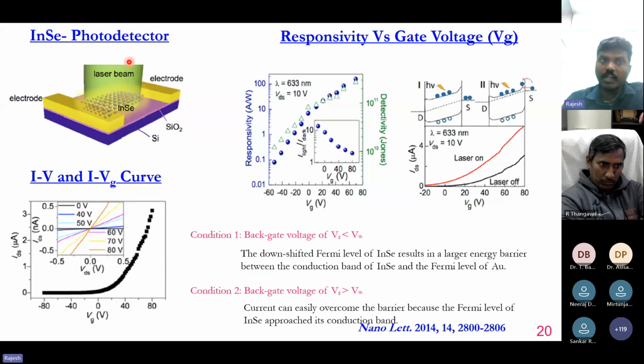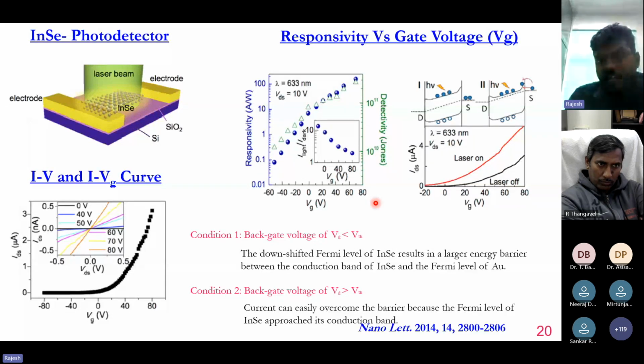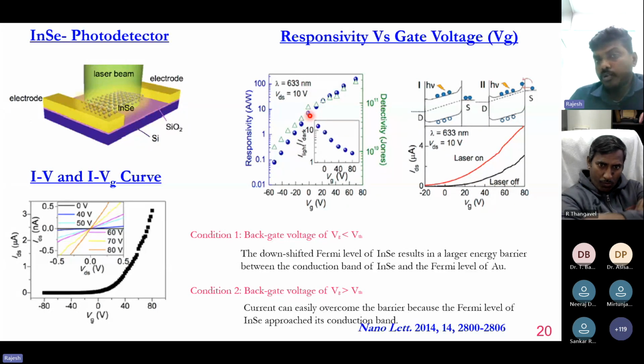Then we shine light on our transistor and try to extract the photoresponsivity. As we can clearly see, when we increase from negative to positive, we observe an increase in the photocurrent as well as the responsivity. When we calculate the responsivity, it is very good, high in number.